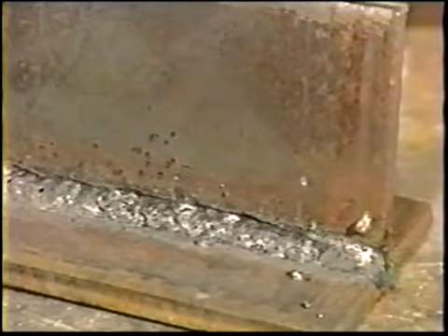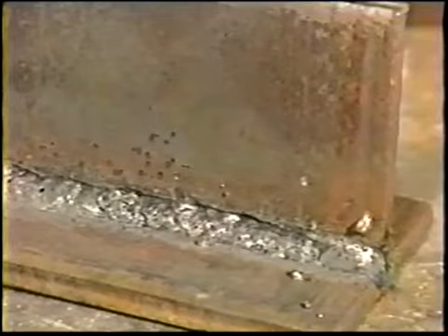Undercutting is sometimes encountered on fill and cover passes. To avoid this, use a Z weaving motion, pausing just long enough on each side to fill the undercut areas. Also, hold a very short arc length and avoid too high a welding current. In the flat, horizontal, or overhead positions, it is best to use a stringer bead technique. If the bead becomes too large, use a smaller diameter electrode. On multiple pass joints, be sure to completely remove the slag before each new pass.